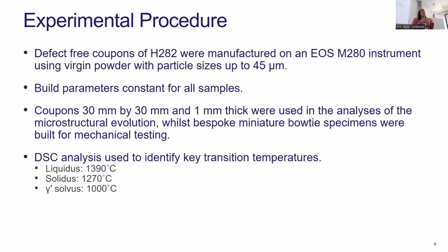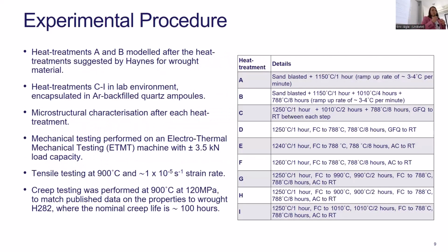So we're looking at equivalent microstructures in terms of thickness to what we're testing. We did some DSC analysis to help us identify some of the key transition temperatures for the material and then design our heat treatments from there. So the liquidus of the material was about 1390, the solidus 1270, and the gamma prime solvus was at about 1000 degrees Celsius, which helps just pinpoint a few things.